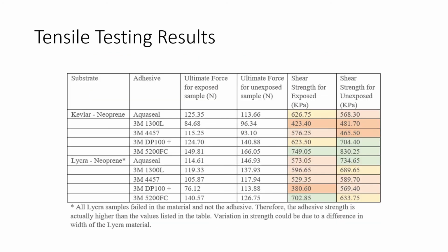The tensile test results revealed the strength characteristics of each adhesive. Unfortunately, the Lycra samples failed in the material before they failed in the adhesive. For most of the samples, the Lycra material failed at a similar shear stress to the adhesive from the Kevlar samples. Therefore, it should be safe to use the same adhesive for both substrates. However, the Lycra in the 3M DP100 Plus failed much lower than the adhesive in the Kevlar sample. Therefore, the same conclusion cannot be drawn for this sample.